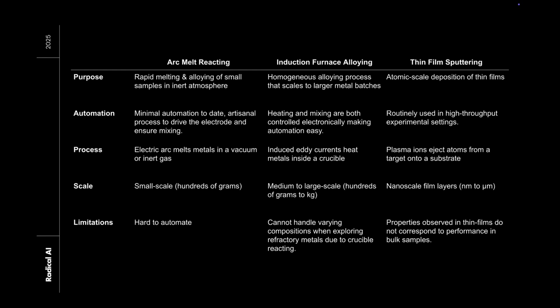And then at the bottom end, we have thin film sputtering. This is an easy to automate experiment. Lots of high throughput or combinatorial studies in alloys have used sputtering experiments because you can cover a huge compositional space and get a lot of great insight. But the challenge is that unless you're interested in coatings exclusively, the thing that you are making is not industrially relevant.